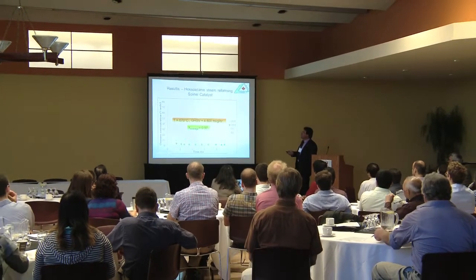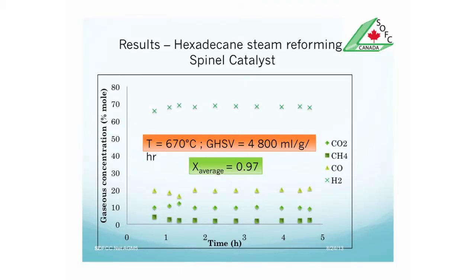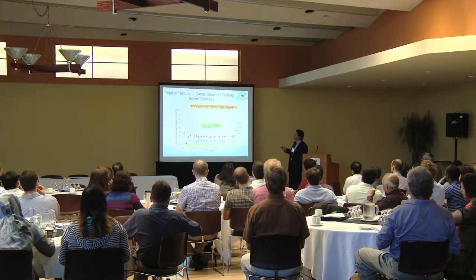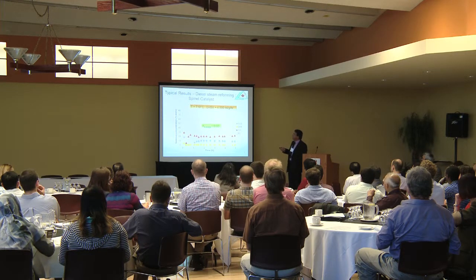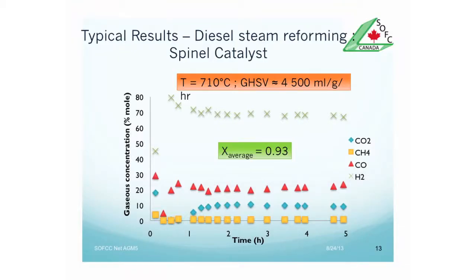So this has been tested. The catalyst has been tested with hexadecane as a surrogate of diesel with very good results. Then we switched to commercial diesel, and we have obtained very, very good results at very low temperatures and relatively acceptable gas hourly space velocities. This means typically less than 1 second residence time of the reactive gas.